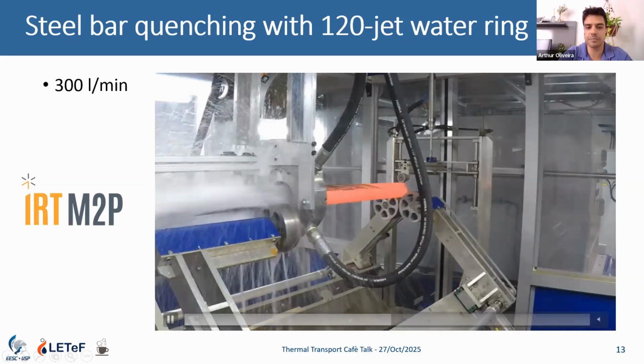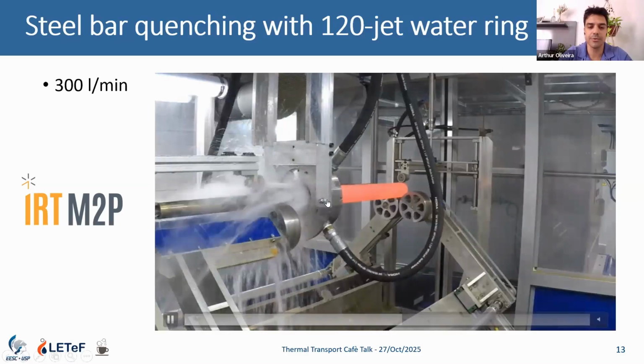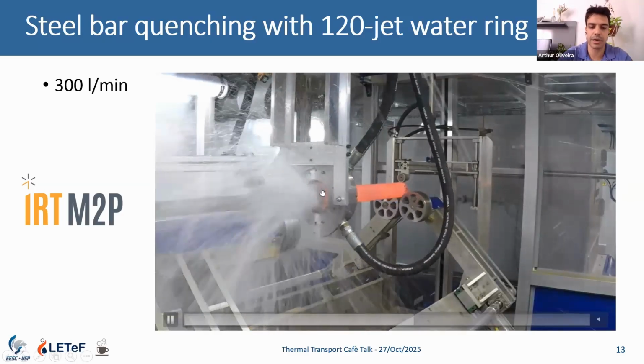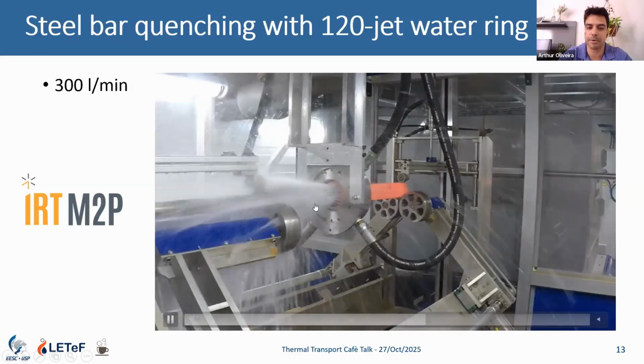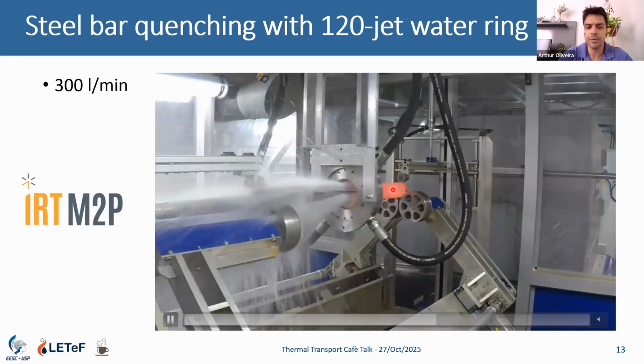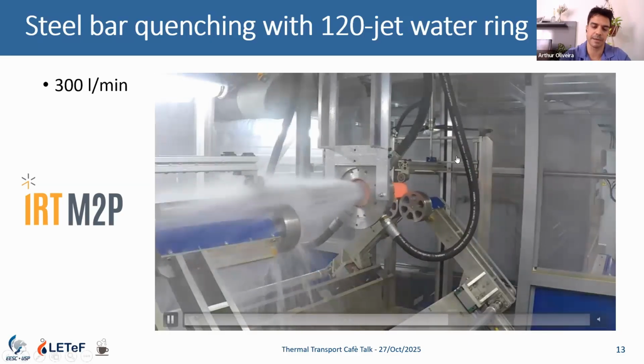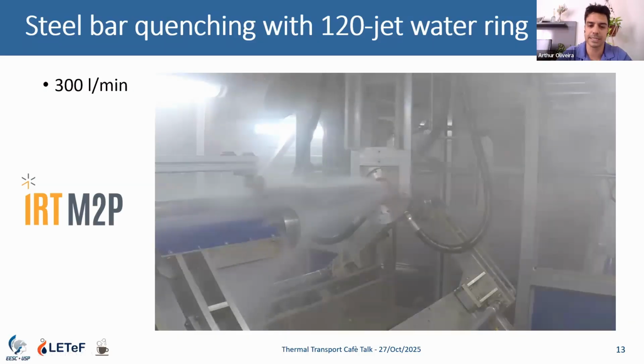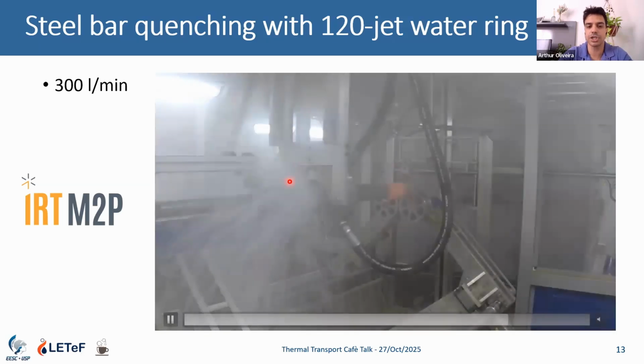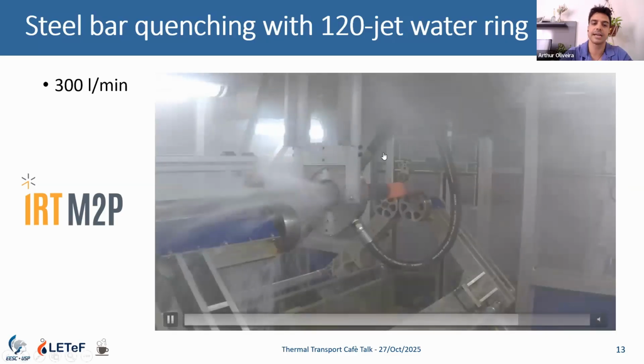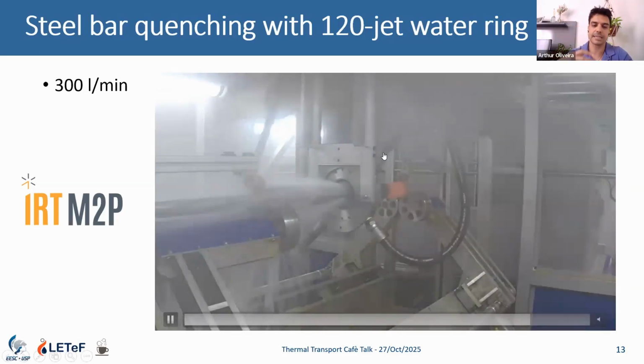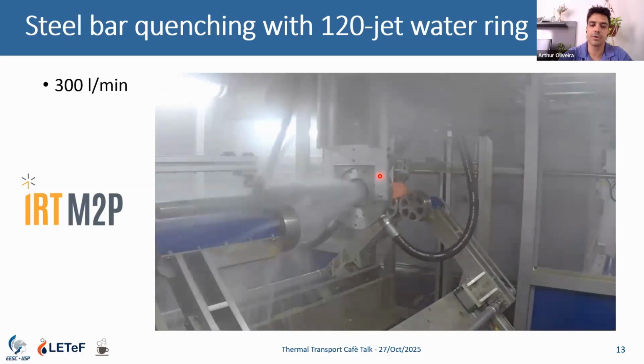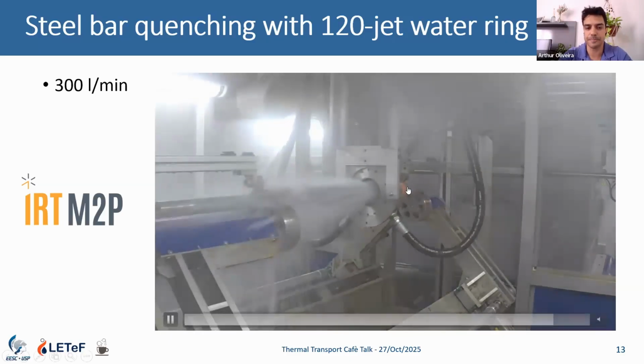During this process, we start the temperature measurement, acquiring the temperature measured by the thermocouples during this cooling process. We have to remind that in an industrial process, you have several rings and the bar passes inside these rings. To simulate this, after finishing sweeping the bar, the ring comes back to the start position and starts sweeping again, several times. It lasts about 2 minutes, going back and forth, and we are acquiring the temperature.